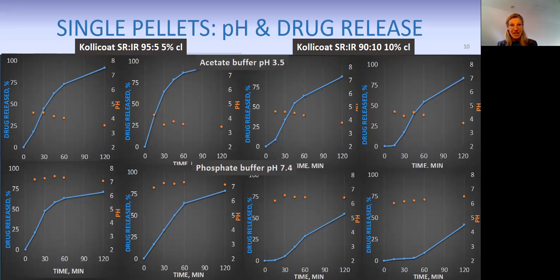And you can actually see that when we expose the 95:5 coated pellets to acidic medium, drug release is rather complete. The pH within the pellet is going towards 3.5. And the other pellet here is showing even faster release than the first one. So we actually have a difference in the individual drug release, which has been hidden in the ensemble of pellet release. So we have a difference in the behavior between the two different pellets.